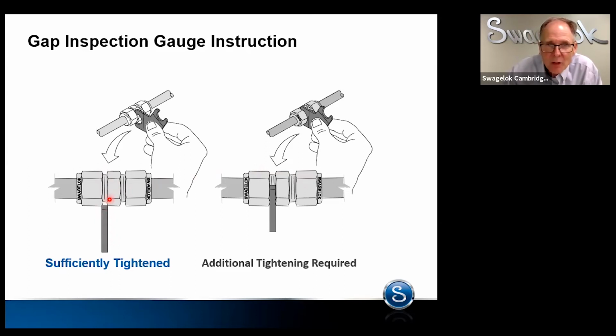Now, it won't tell you if you've over-tightened the fitting, but with stainless steel, the number one problem with leakers is typically under-tightening the fitting, especially if you get into a little heavier wall thicknesses on the larger sizes. It becomes somewhat difficult to pull it up, and the tendency is to under-tighten than over-tighten. If a fitting is under-tightened, you'll insert the gauge and you'll see that it'll fit in between the nut and the body hex. Fitting needs to be tightened up till that gauge does not go in. So again, it's a simple device.